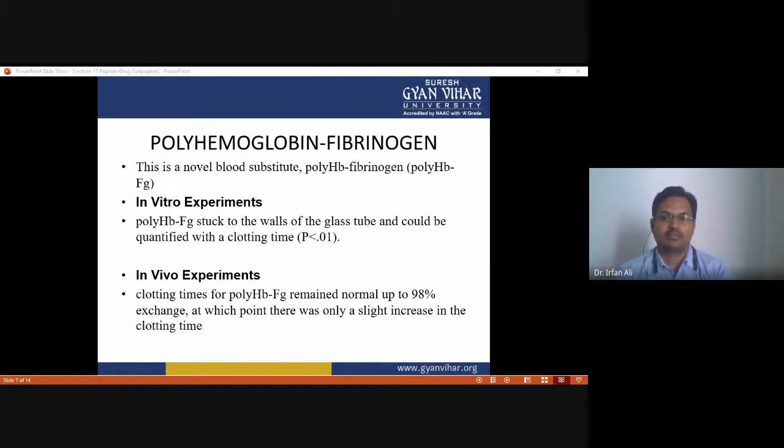After 24 hours of polymerization, the reaction was stopped by quenching with 2 molar lysine solution in a molar ratio of 200 to 1 lysine to hemoglobin, and the solution was then dialysed against Ringer lactate solution overnight to obtain the